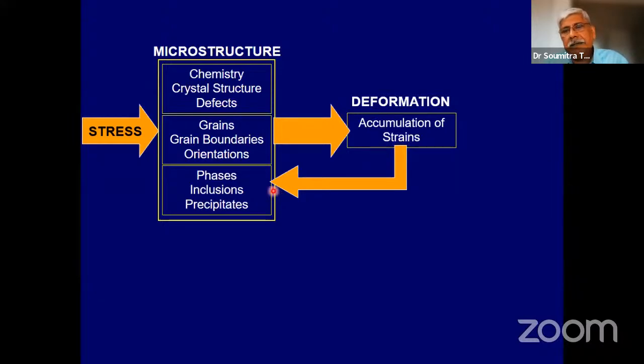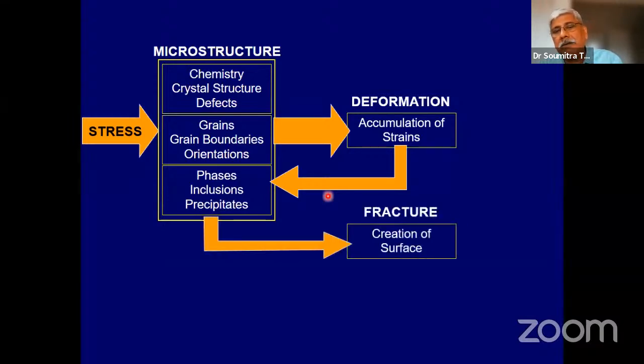That damage will be reflected in an increase in, let's say, the dislocation density, so some of the defects in the microstructure, or changes in some of the inclusions that you have, the phases that you can have, the phases can transform. There can be changes in the grain orientations, the grain boundaries, they can slide, they can move, they can grow, and so on and so forth. And that constitutes damage. When the damage reaches a critical amount which can be tolerated, then fracture or failure takes place through the creation of surface.